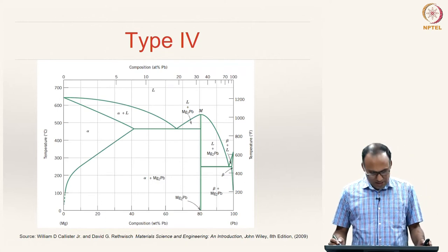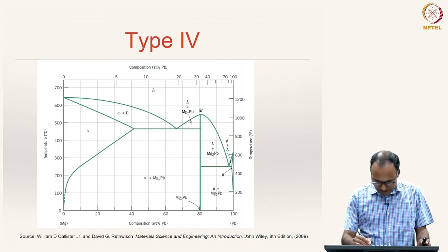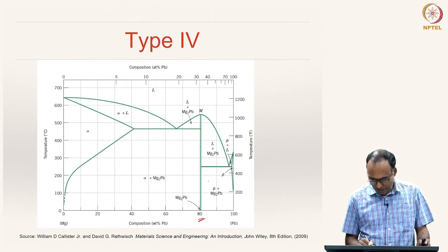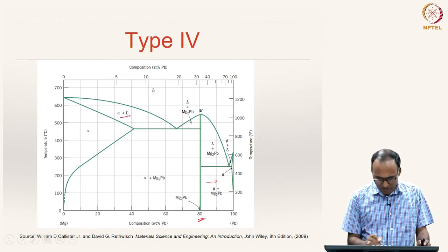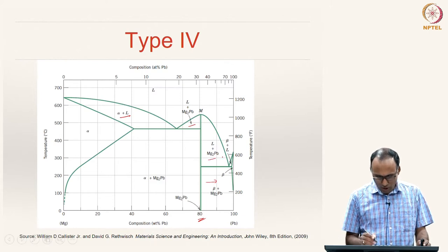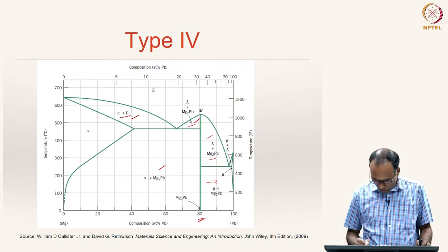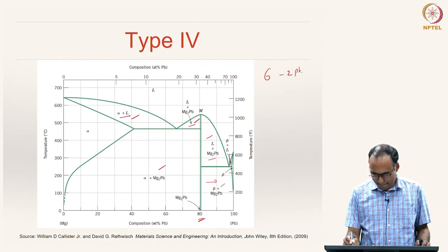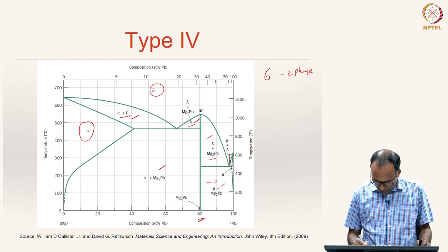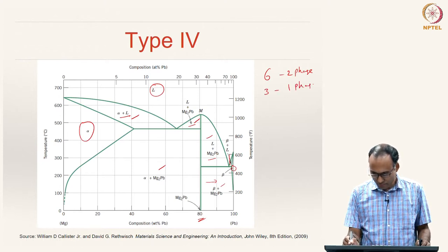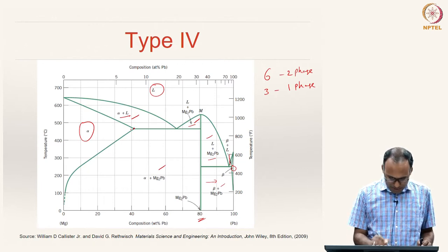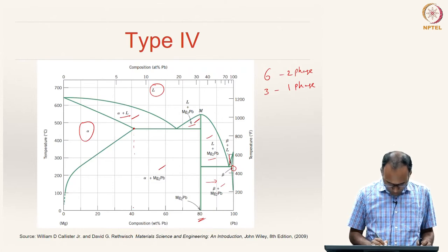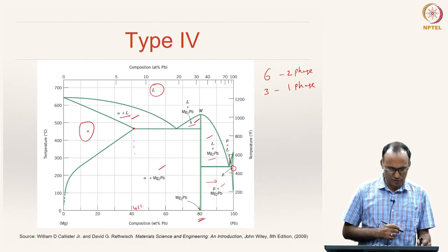Such systems do exist. For instance, in the magnesium-lead system, you can clearly see that Mg₂Pb is our intermetallic. Left of that is one sub-system, and right of that—between Mg₂Pb and beta solid solution—is another sub-system. You can identify all two-phase regions: alpha plus L, L plus Mg₂Pb, Mg₂Pb plus beta, and so on. There are six two-phase regions and three single-phase regions. The solubility of B in A is maximum at temperature T₁ (about 41 percent), and as temperature decreases the solubility reduces.